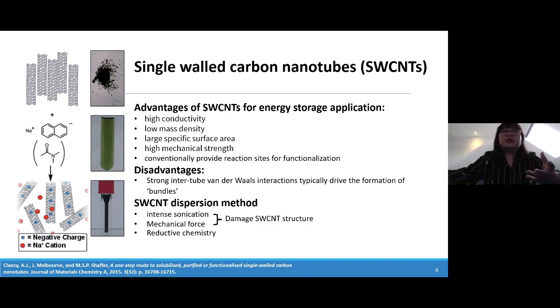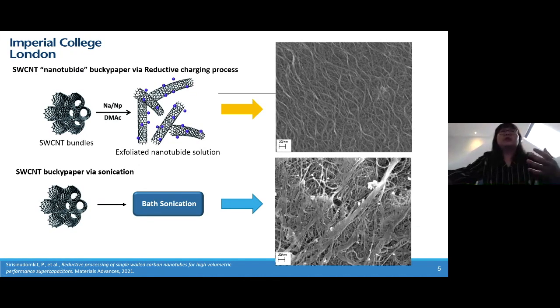To make it a clearer picture, I made single-wall carbon nanotube bucky paper with the same concentration of carbon but a different approach. The first one is called the reductive charging process. Using dimethylacetamide as the solvent and charging with sodium naphthalide as the reductive agent shows that the bucky paper formed has well-connected structures and is more individualized, compared to the single-wall carbon nanotube bucky paper made via bath sonication at the same carbon concentration, which still has lots of bundles and impurities on top of the surface.